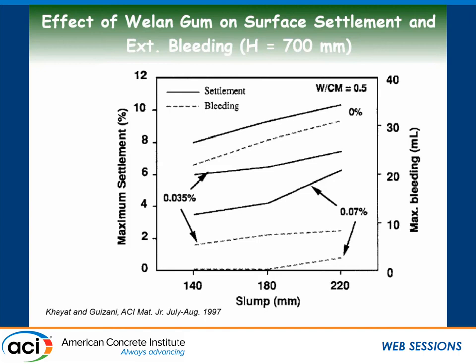Now if you look at the other y-axis, which is bleeding, this is bleeding that is collected at the surface. We don't always have the pleasure of having bleeding at the surface. And that's what you want to see, at least: no bleeding. But if you have bleeding, again, you have the dotted line, 0% VMA. And if you add some VMA, and if you add even more, you can eliminate bleeding. But elimination of bleeding up to 180 doesn't mean that there's no settlement. So it still has consolidation and segregation.